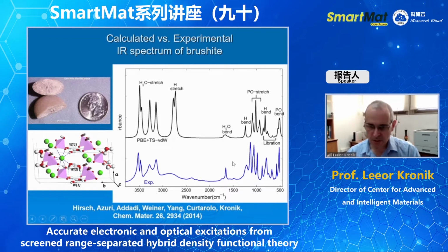And here you can see that on the computer, we could have a simulated spectrum. That's the black one, which is in great agreement with the experimental one, even in this region where there are really many, many features. And so we could really assign individually where each feature is coming from.